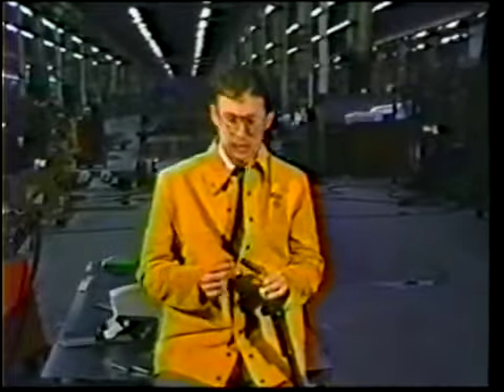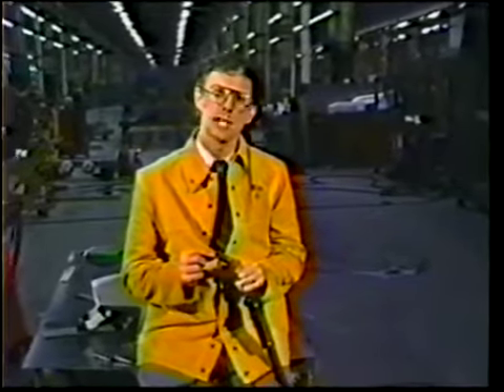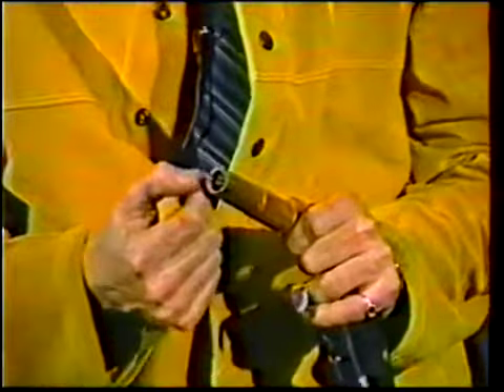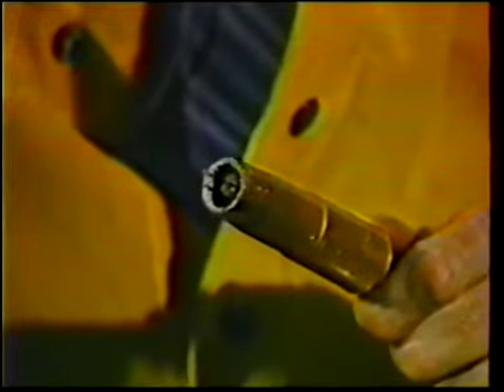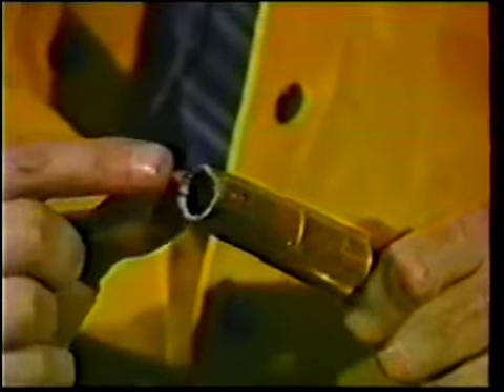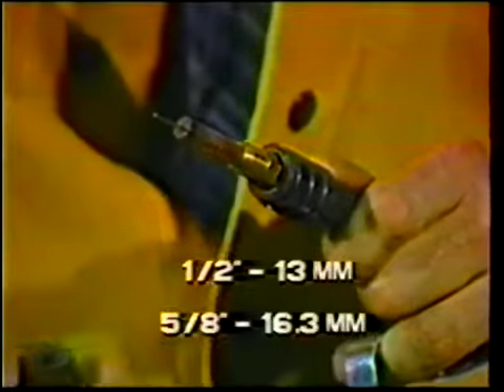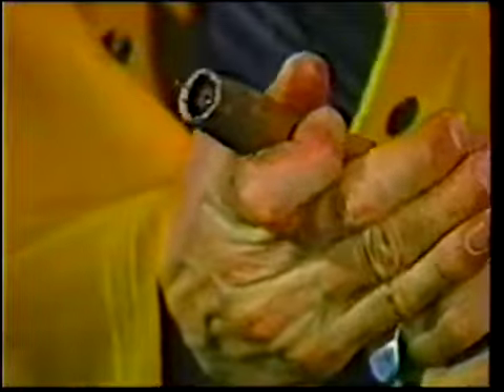Can you remember where we set the contact tip for short circuit welding? Slightly outside the nozzle, keep the wire stick out short. Spray transfer is the exact opposite. We should set the contact tip slightly inside the nozzle, maybe about 1/8 of an inch down inside the nozzle. Two reasons for this. One, we need a longer stick out because we no longer short circuit. And the other reason is we want to protect the contact tip from the intense heat. The wire stick out should be 1/2 to 5/8 of an inch in length. When you put the nozzle on, make sure the contact tip is slightly recessed.